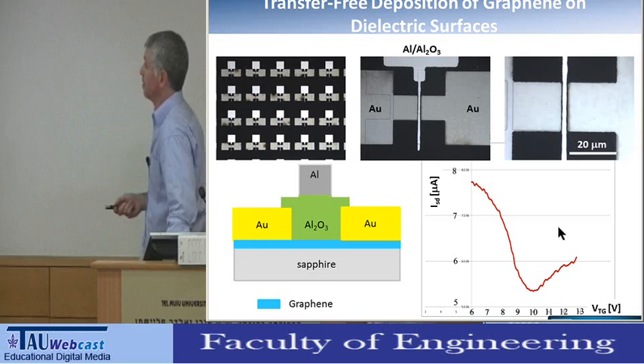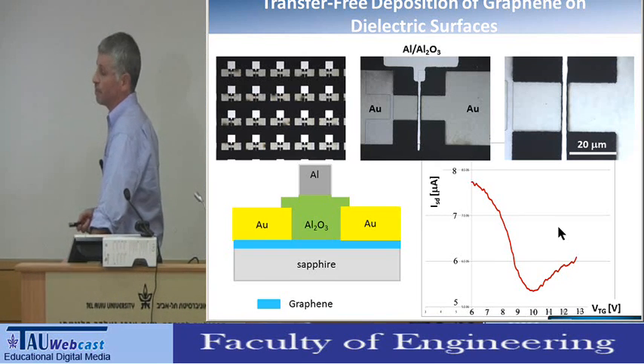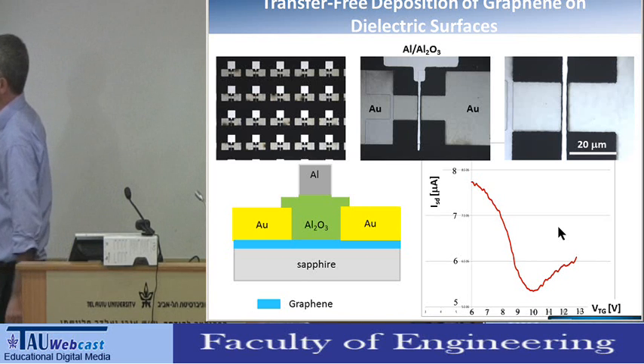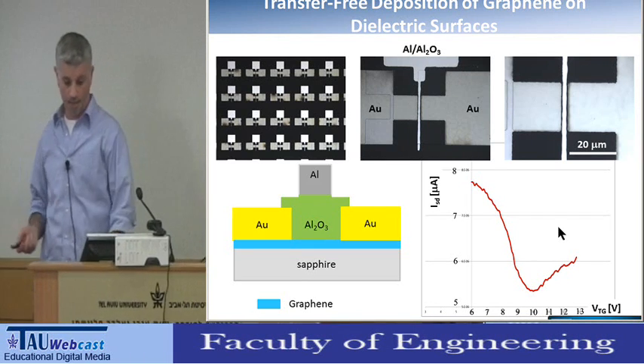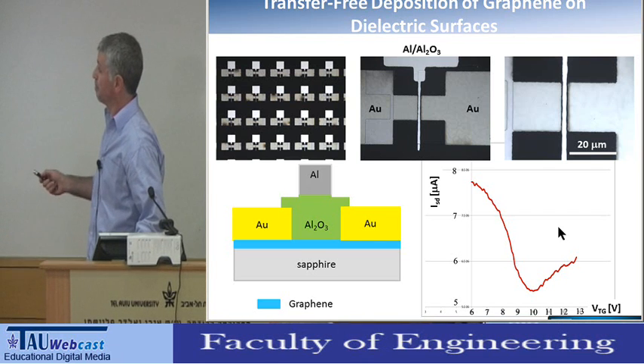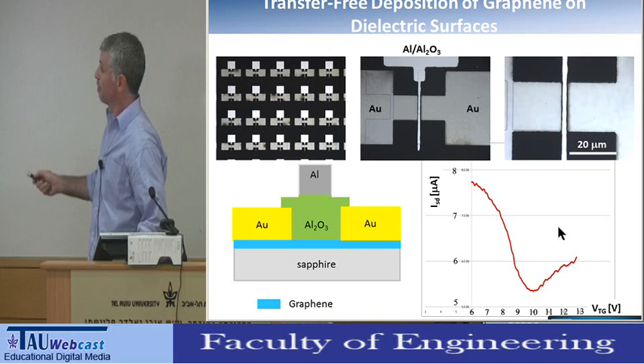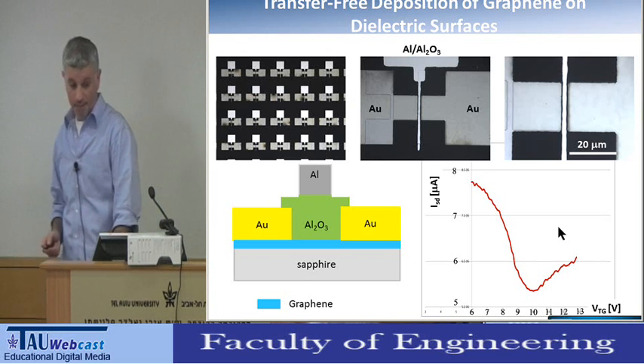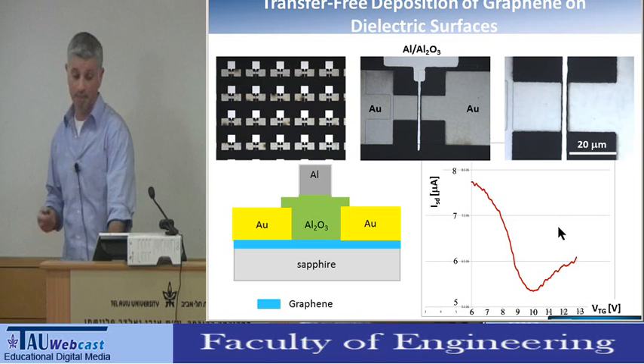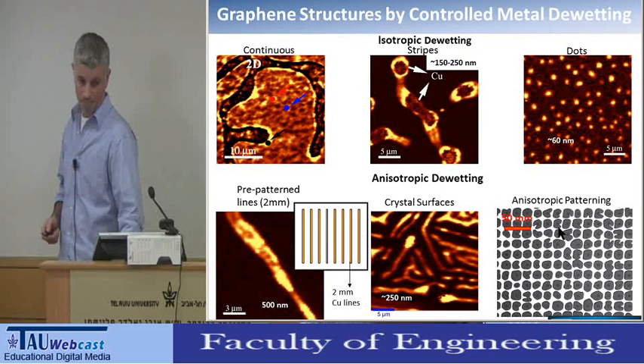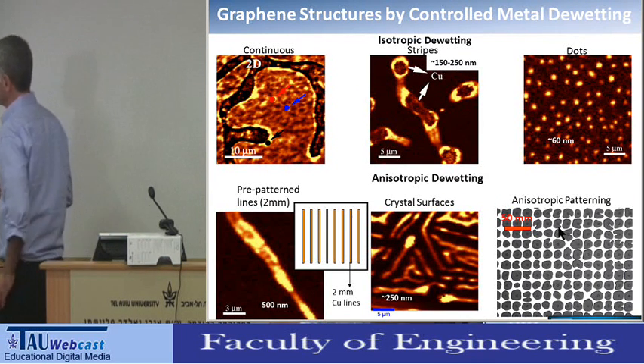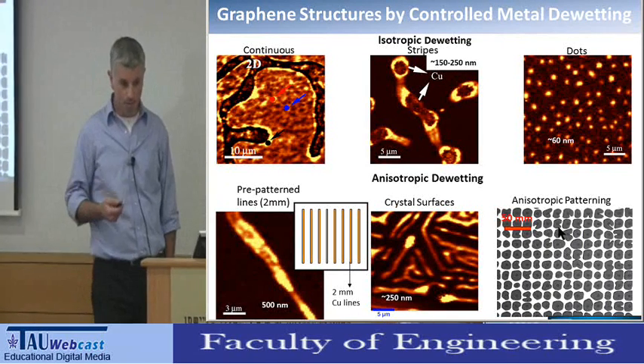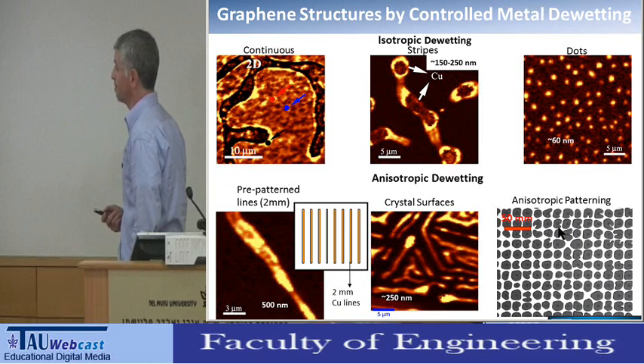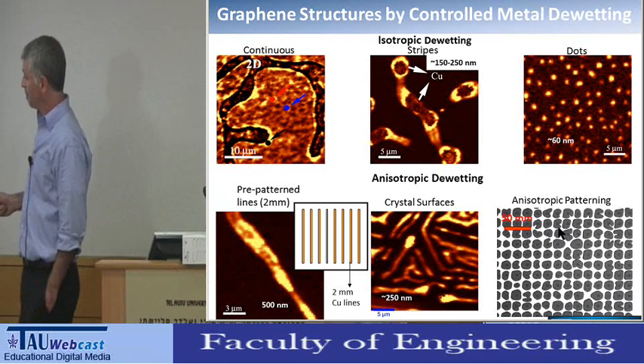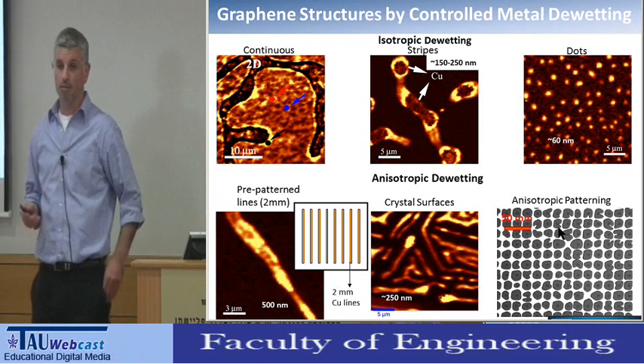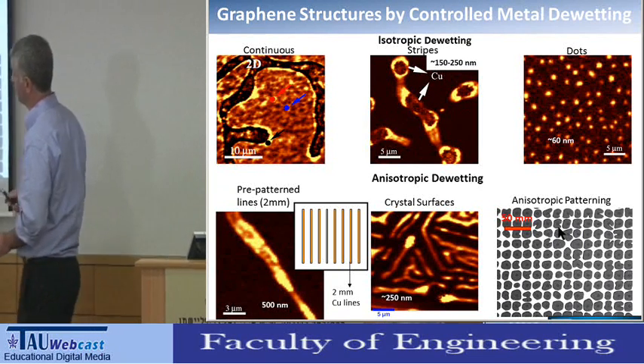Then we could show that, as in every case where you synthesize large-scale graphene, you can make a series of devices and characterize them. In this case, by making source and drain gold electrodes and a top gate made by ALD deposition of alumina and aluminum as a gate electrode. But more interestingly, you can use this methodology to control the dewetting and to form different graphene patterns directly on the surface without any post-lithographic step.